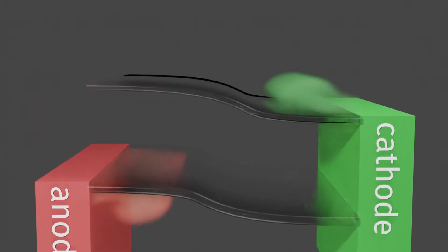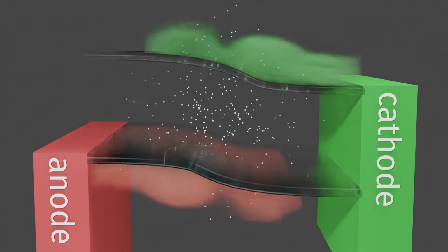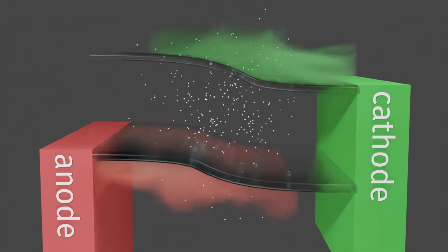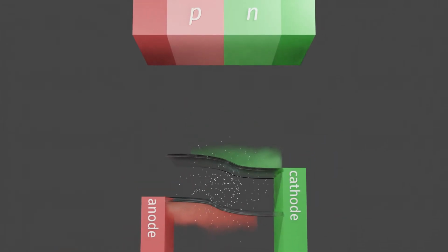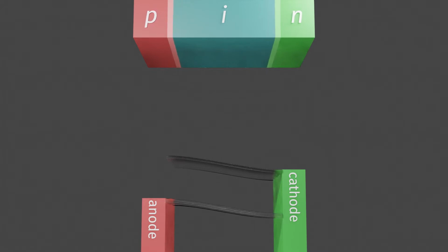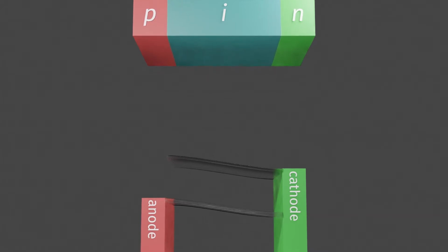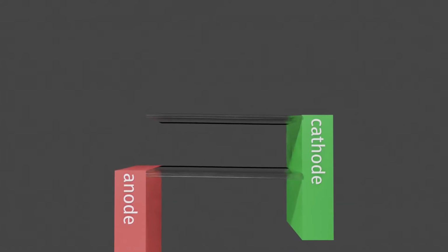Conventional laser diodes replenish the supply of electrons and holes needed for emission via a diffusion current and have heavily doped active areas. For organics, the high doping levels are still required for ohmic contacts, but any dopants in the active layer would quench emission. Without dopants, the band diagram looks like an insulator.